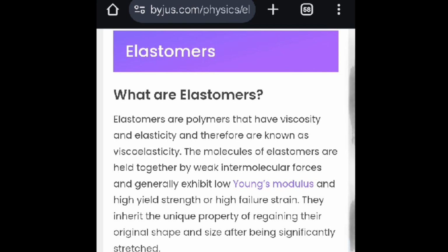Even the most flexible brands that I've ever been able to find, the ones containing the highest SBS contents, never mind all their other faults, the stretchiest of them all does not reach 100% elongation. Therefore, it can't qualify as elastomeric under the definition of can it stretch to 2 times its size, which is the basic, most agreed upon definition: its ability to stretch.